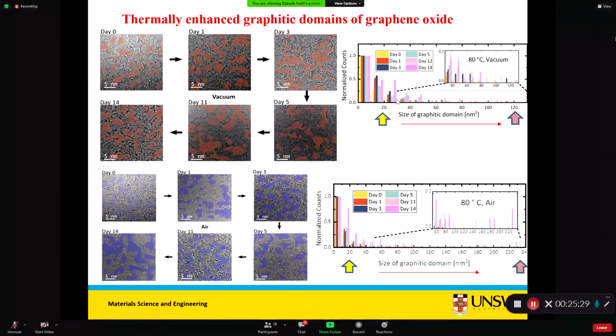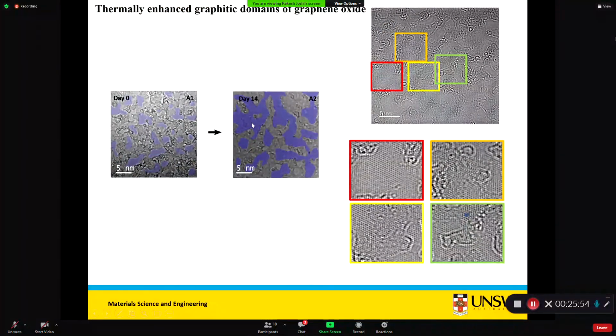And here the vacuum one doesn't give more large domains of the pure graphene, whereas the air annealing, at 80 degrees centigrade, gives graphitic domains from 20 nanometer graphitic domains in pure graphene oxide to 200 nanometer square in air annealed graphene oxide. And if you see here, this is the day 0 and day 14.